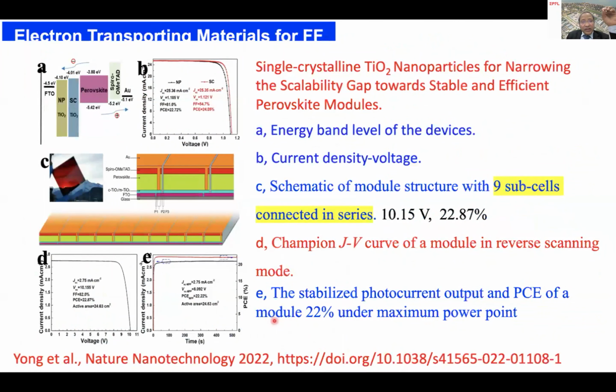So here we developed nanocrystalline TiO2 materials. The difference is the conductivity when compared to the colloidal nanoparticles. The conductivity of the TiO2 nanocrystalline materials is enhanced significantly. As a result, you see the enhanced fill factor, a property I have not mentioned before. The fill factor increases, and the increased fill factor enhances the power conversion efficiency. And also you can see the 9-cell module gives 10 volts, and the efficiency of this module is 22.87%.